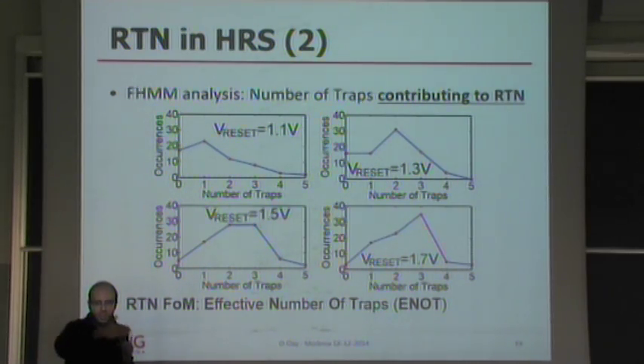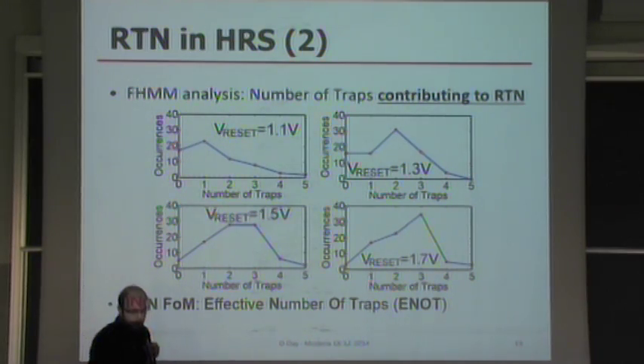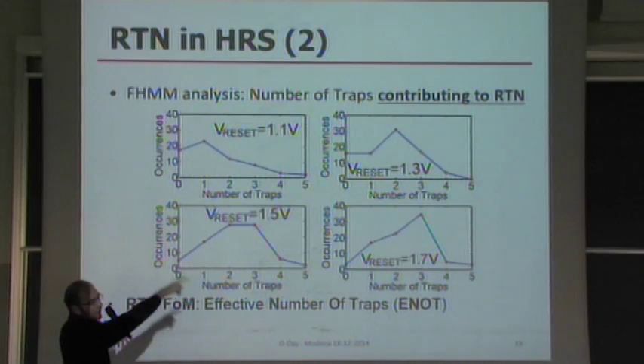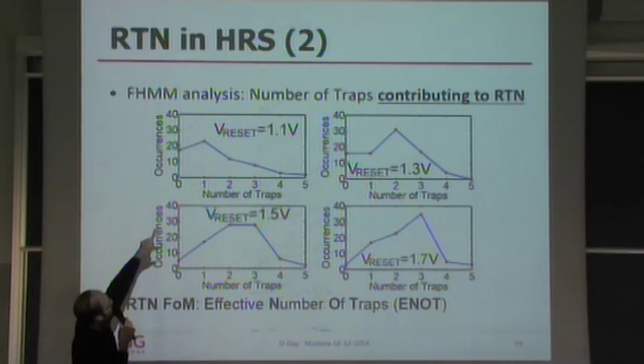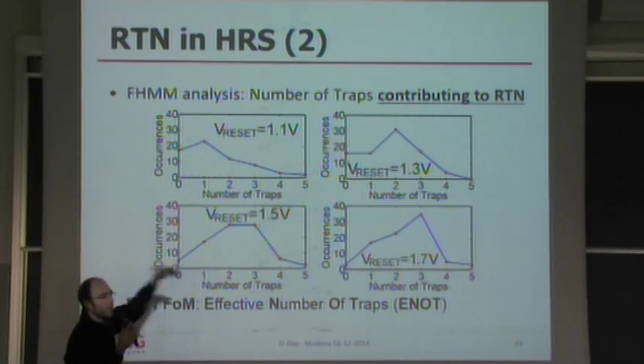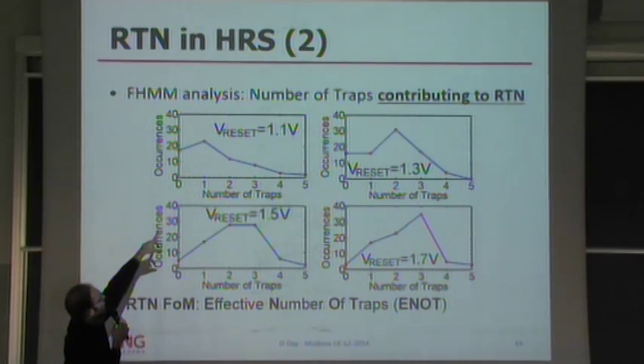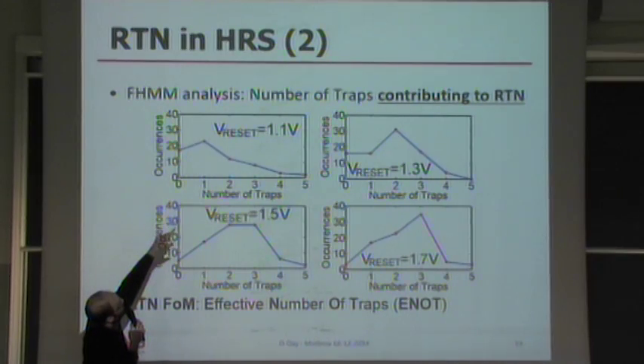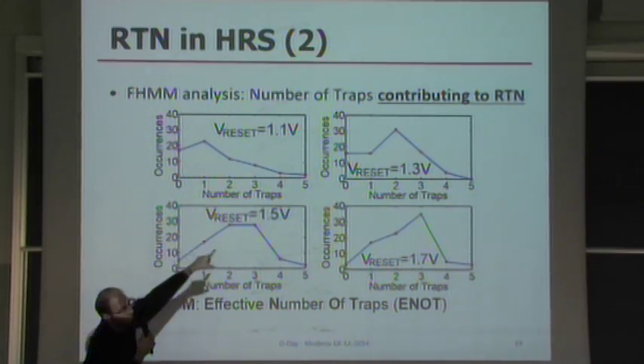For every RTN trace, we can have a given number of traps. We don't know it, but we can plot it for different conditions of the device for 100 switching cycles. So in this graph, we see that most of the times, out of 100 reading operations, we have one trap. Some other times we have 2 or 0 traps. Less often we have 3, 4, and 5 traps.